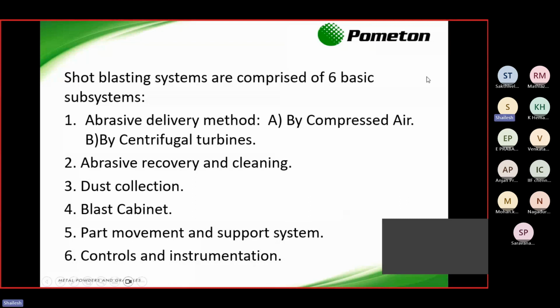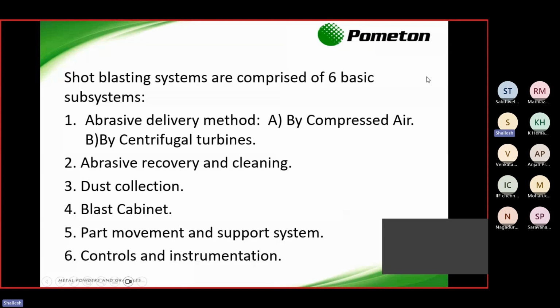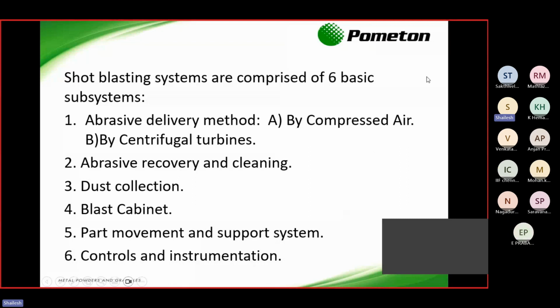It totally depends on what kind of component you want to blast, what Ra value and Rz value you require for the blasting, how aesthetic a look you want to see, and whether after shot blasting it will go for painting or other coating applications. If we consider painting and coating, most industries use stainless steel shots for this type of application, because MS shots, meaning mild steel shots, have more carbon content. After blasting, it definitely spreads some carbon layer onto the components, which will affect the coating, like peel off, and proper painting and coating cannot be done.